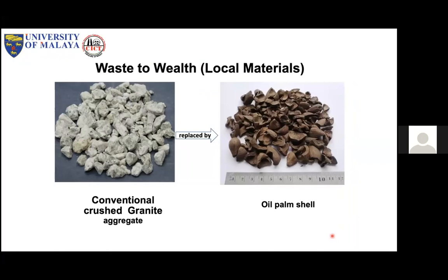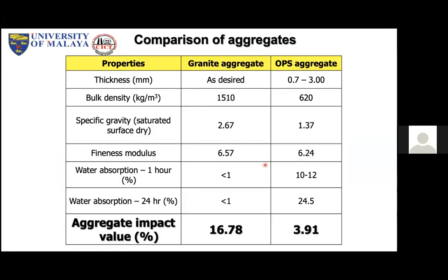So we did test, comparing this aggregate and this aggregate. This is the normal weight aggregate, and this is the shell aggregate. This is actually biodegradable material, please remember. And the density is only one third to half of this, whereas the aggregate impact value enabled us to understand that this has a lower value compared to the high value of the normal granite aggregate.